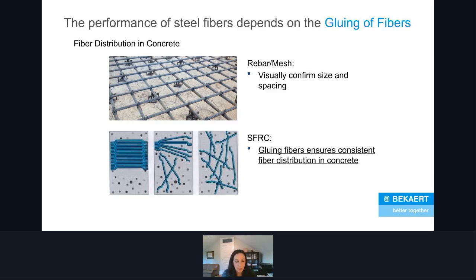So in this bottom left image, you can see what's known as a clip of steel fibers. They're glued together with a water-soluble glue that as these are dosed into the wet concrete mix, so this shouldn't be one of the first components of the mix, it should be one of the last ones added. And as these are added into the mix, after about 5 minutes of mixing, the glue will start to dissolve, and each of the fibers will break off and distribute in that nice, even, consistent way that we count on.